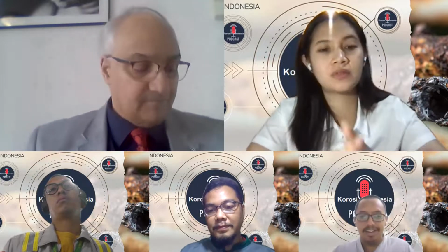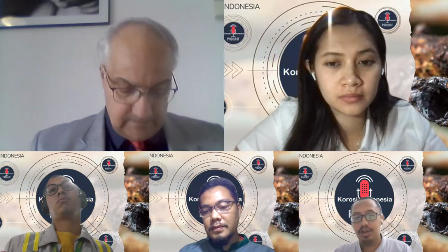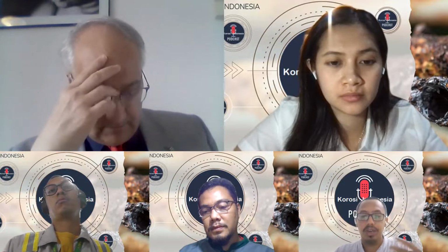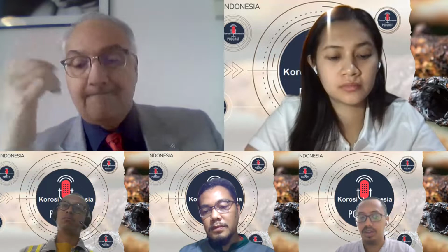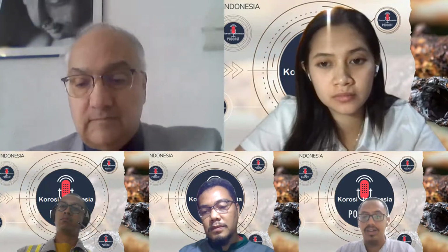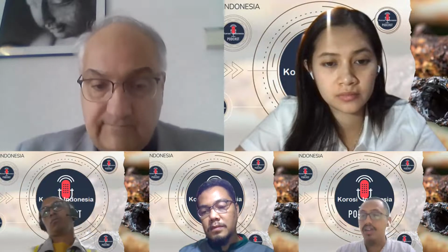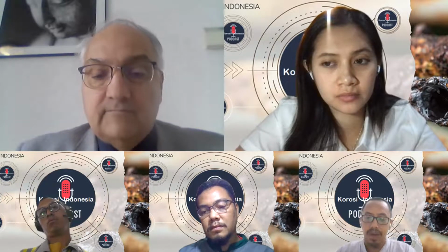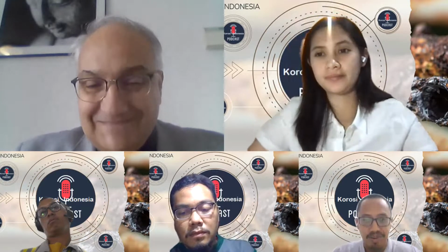Okay, thank you, Pak Sina. Basically, this is a very tricky question, and difficult to answer. But in my opinion, in almost all cases, MIC produces localized corrosion. So any NDT technique that can detect localized corrosion is applicable, such as UT or corrosion mapping. But please note that a major drawback to all monitoring techniques is that one only monitors the location of the probes or the accessible areas offered for inspection. These will not necessarily be the areas that are colonized by the destructive microorganisms. So please consider that. I think that's the answer from my side.